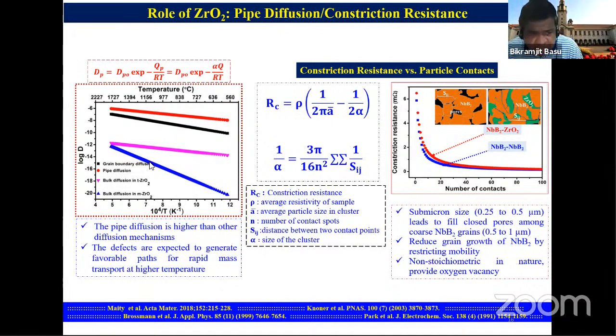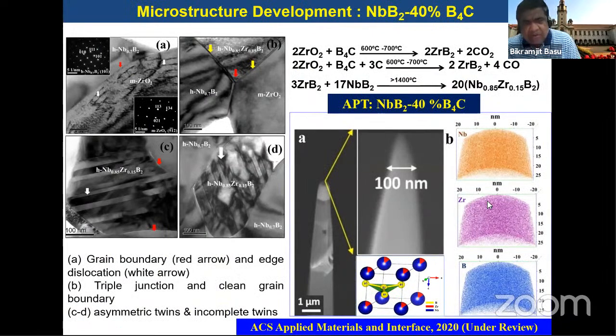Subsequently, we have done some calculations of the activation energy of diffusion, and we have found that pipe diffusion is, as expected, much higher than the other diffusion mechanisms in these kinds of systems. Now, taking it forward, we have developed niobium diboride-based composites with boron carbide as a second phase addition. When we added different amounts, like 0, 10, 20, 30, and 40%, we saw that with around 20 to 40% addition of boron carbide, a new intermetallic phase forms, which has a composition of niobium 0.85, zirconium 0.15, boron 2.